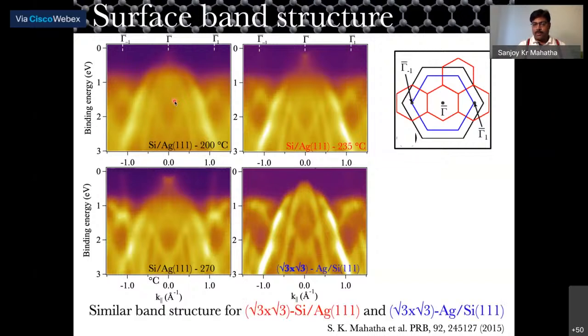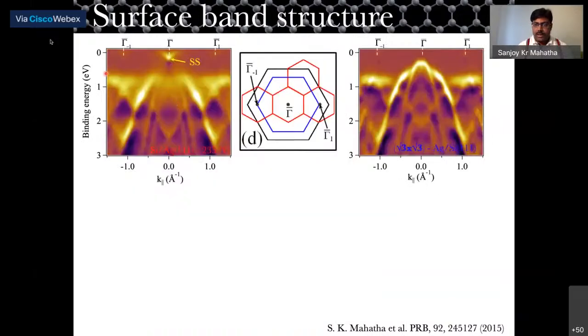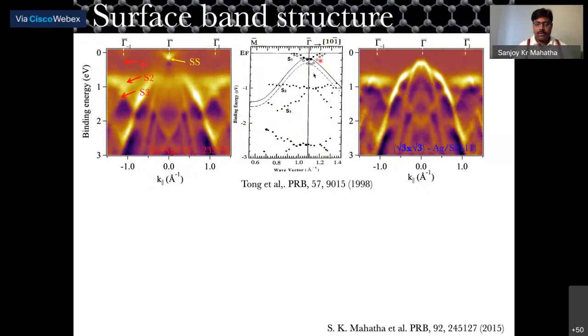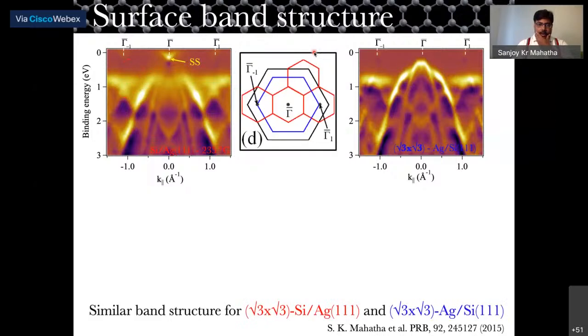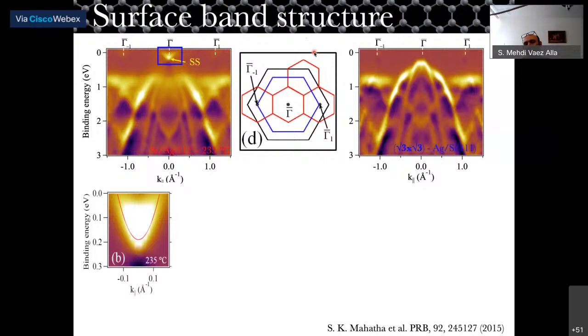So there must be some silver which is going on top of silicon when we are growing at 200 degrees centigrade. And even if you compare this band structure at different temperature, every band one can compare with the reverse system with √3 by √3. And from here, at gamma, you see a surface state, which you can compare from this theoretical calculation. This S1 band is this one, this is S2, and these are S3. And this calculation was done on √3 by √3 silver on silicon, the reverse system. And from here, we can say that we could not also match the effective mass.